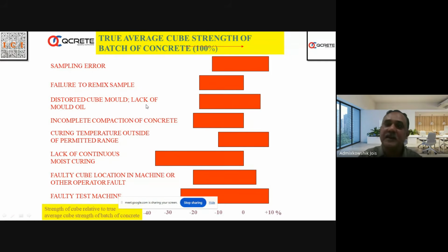Distorted cube molds, lack of mold oil, or if somebody uses a bad mold oil, it may have an effect in the initial stage itself on the surface. You may see a lot of air bubbles, and it may also sometimes react with the surface of concrete, leading to surface erosion or surface retardation, and it may affect the strength. Sometimes even 1 MPa, 2 MPa will make a difference in acceptance or not acceptance. So it is very important that we use the right oil. There are many companies who are supplying good mold release agent. We have to use standard mold release agent.